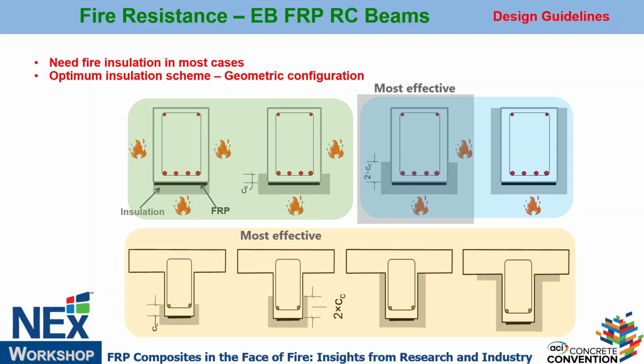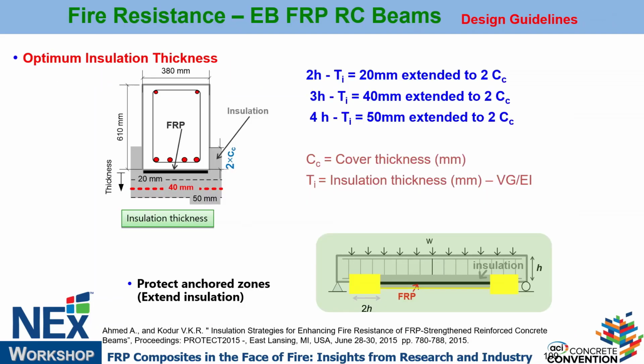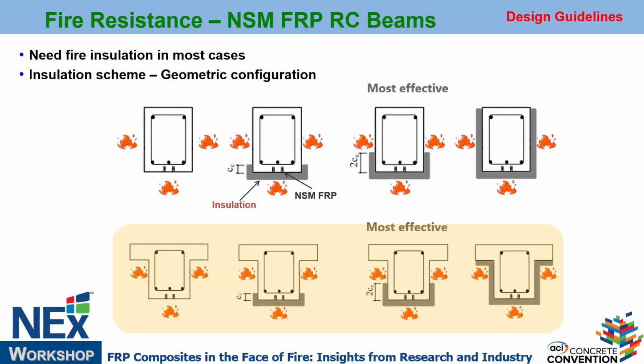We experimented with it with test models. Same thing for T-beams as well. How much do you need? With EB, if you need 2 hours of fire resistance, you need 20 millimeters of insulation. If you need 3 hours, 4 hours, more, but you make sure you extend it on the sides as well. At 2 CC, 2 times the concrete cover thickness as per ACI 318.